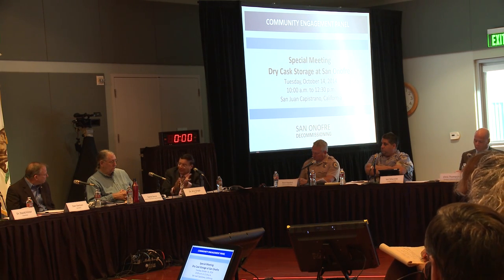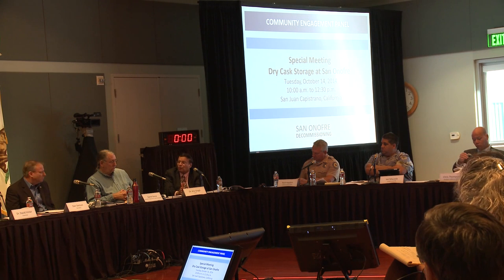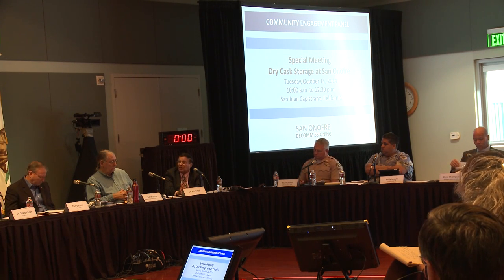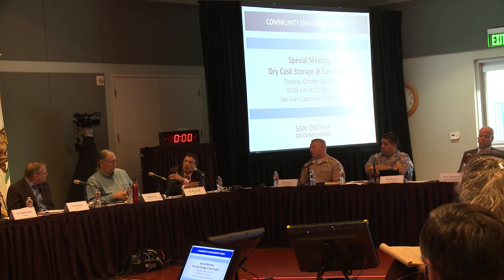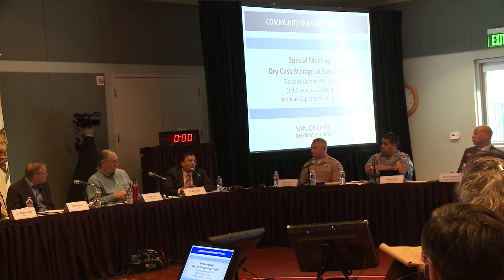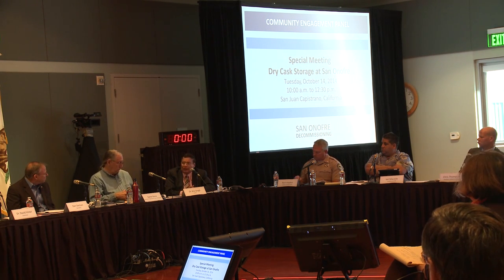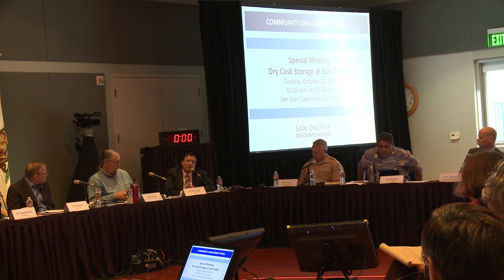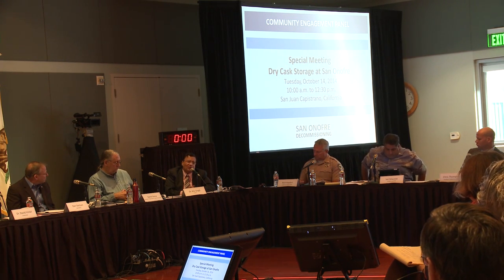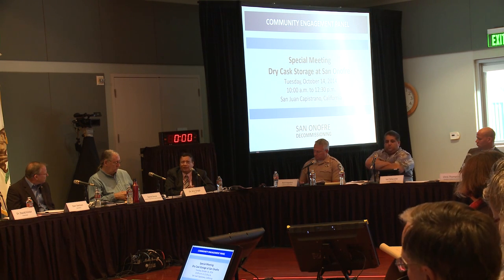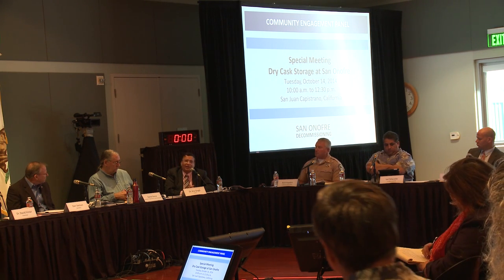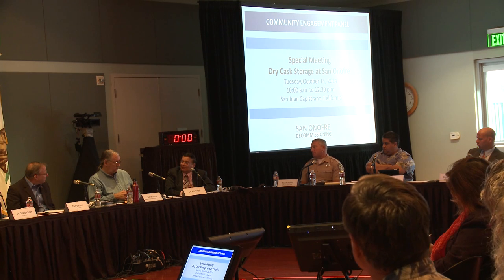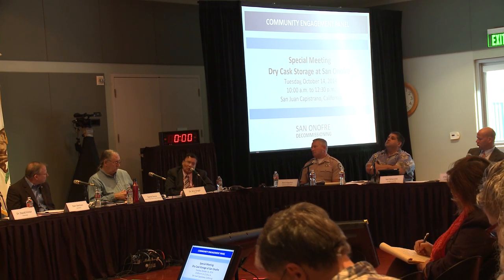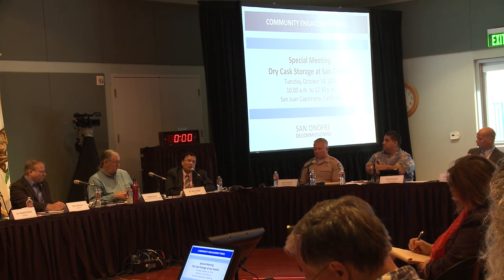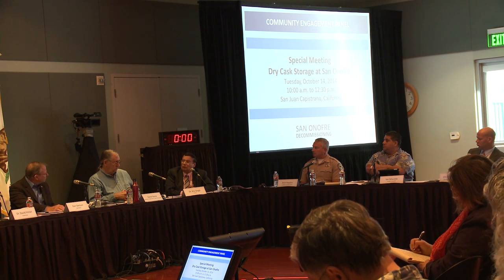I can only speak to the data we have. First, the data is relatively limited. The canisters have been in use only for a few years, and the accumulation is very minor. The general evolving consensus in the industry is that you need to have 500 milligrams per square meter. Here we are in the order of 5 to 20 in that range, so we don't have much accumulation. We found the canisters to be shiny, no evident damage.